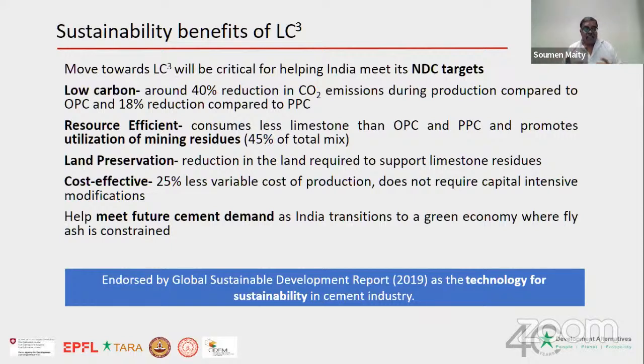LC3, of course, is always low carbon. It has a potential of reduction of around 40% CO2 emission. And in certain cases, what people have also reported is that it can even go beyond 40%. Because when you are calcining the clay, if you can use renewable biomass as a fuel, because the temperature is low, around 800 degrees centigrade, we have done trials with it. We were successful in using waste biomass. And if you can use that, then the amount of emissions is also going to reduce higher than 40%. And you can save more than that.